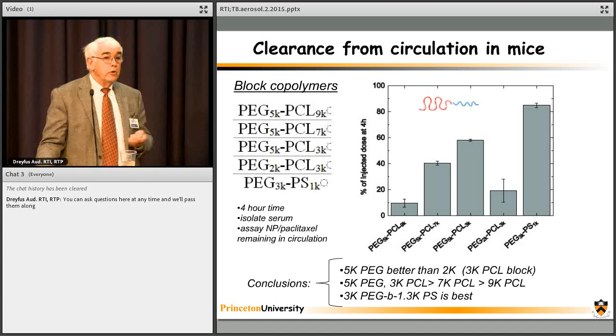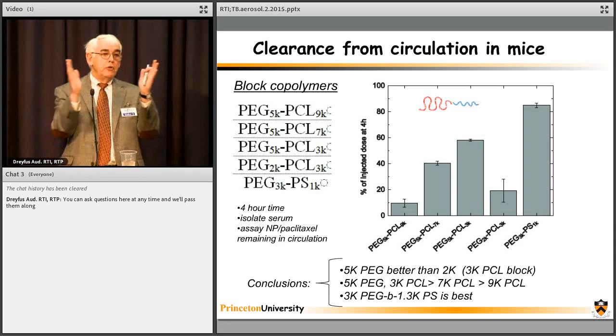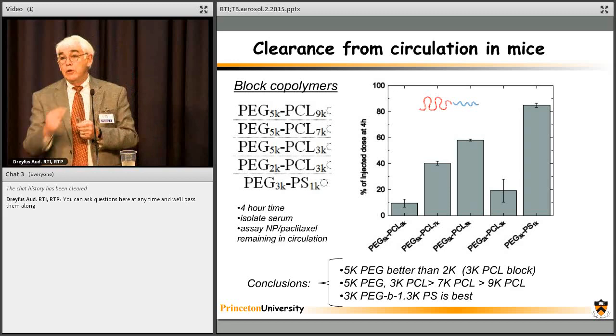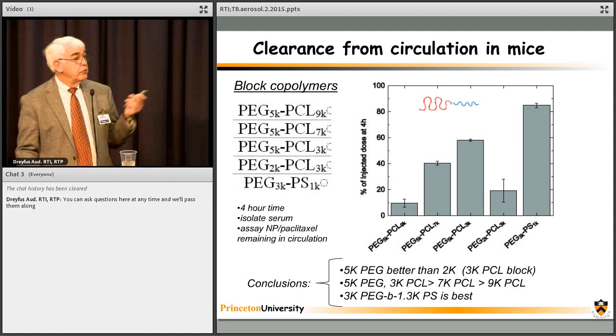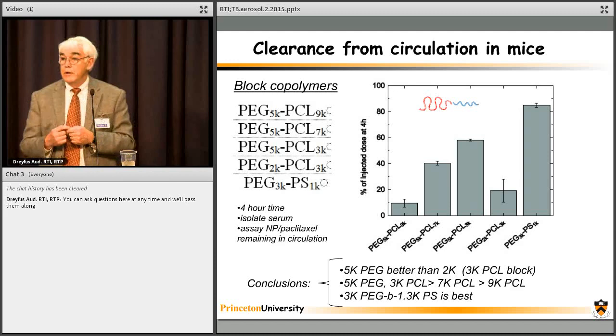Why is that so good? It's so good because polystyrene is actually much more hydrophobic than polycaprolactone. And so it gives you a better anchoring energy, which lets the PEG chains be forced more together. You get a more dense PEG layer. Celator is actually going into their trials with the polystyrene material because of this greater circulation ability, even though the polystyrene is not going to be biodegradable. So it's a trade-off they've made, and they're convinced that these very small polystyrene fragments are not going to be toxic or have any long-term consequences.